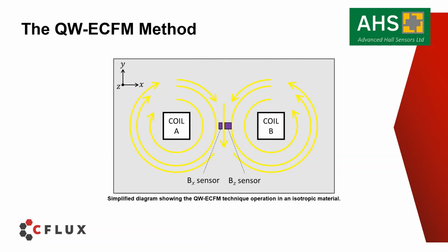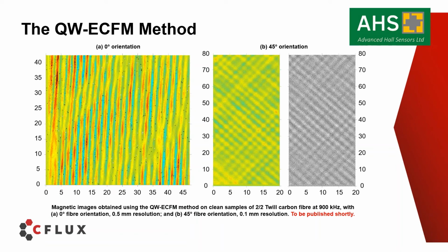These measurements are recorded and compiled into magnetic field images for further evaluation using the positioning information received from the scanner motors. The distribution of the eddy current is highly dependent on the electrical and magnetic properties of the material. Based on the operational range of DC to 4 MHz, this technique is designed to be used for the NDT&E of numerous materials including steels, both ferritic and austenitic, aluminium and titanium alloys, as well as carbon fibre, essentially anything electrically conductive. For carbon fibre, we have found that this technique is particularly sensitive to the 3D orientation of individual weaves, relative to the directionality of the linear eddy current region direction in the y-axis.